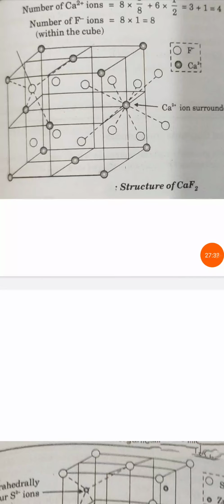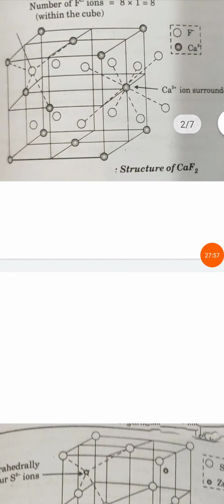For example, thallium chloride crystallizes into forms having NaCl type structure, that is coordination number 6, and having cesium chloride type structure with coordination number 8. These variations cause errors in prediction of the actual structure of an ionic solid because the anions do not act as hard spheres. Instead, they get polarized by cations, which results in error when radius ratio rules are applied.